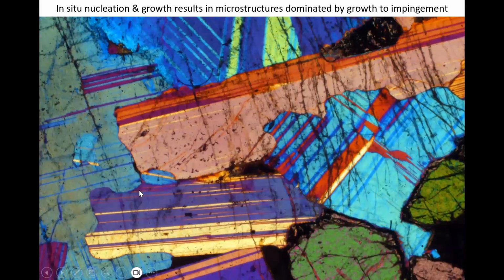So this is just thin section in with the cross polars, really emphasizing that irregularity of the grain boundaries. Here they are, they're going all over the place. They bear no relationship at all to growth faces, and you get a lot of included grains. So there's an included grain there, which is probably in optical continuity with that. So you can imagine this grain boundary is really, really highly irregular, no fabrics, nothing at all.